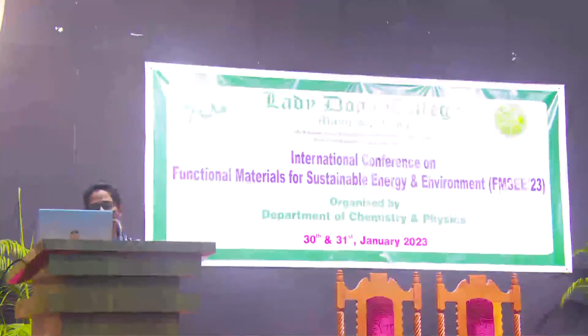Here, copper barium tin sulfide is a kesterite-based solar cell material. The prominent kesterite-based solar cell material is copper zinc tin sulfide. Because of the anti-site defect and binary phase formation, the efficiency is not very good in CZTS. CBTS is a good alternative for that material, yet it suffers from a bottleneck called band gap tailing. This Urbach energy calculation is a proxy for finding the band tails present in the copper barium tin sulfide material.